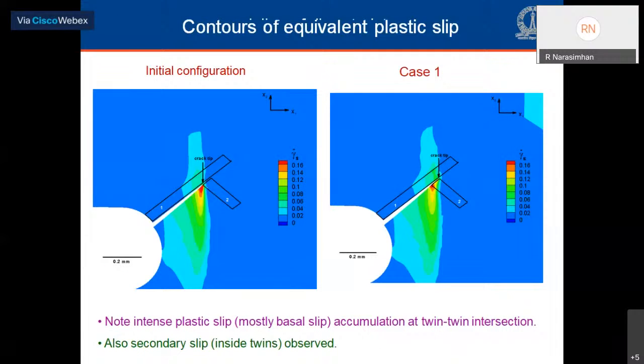Before I show the energy release rate variations, let us take a look at contours of equivalent plastic slip for the initial configuration, the contour plot on the left side in this slide, and the case 1 simulation, the contour plot on the right side. The crack tip locations are indicated in both the contours. The interesting observation here is, if you look at the right side contour plot, there is more intense plastic slip concentration at the intersection between the two twins rather than at the current crack tip. You can actually see the crack has opened up along the twin boundary. Furthermore, we see plastic slip development inside the twins, the secondary slip activity, which we saw in our optical metallograph. That is again evident from these numerical simulation results.